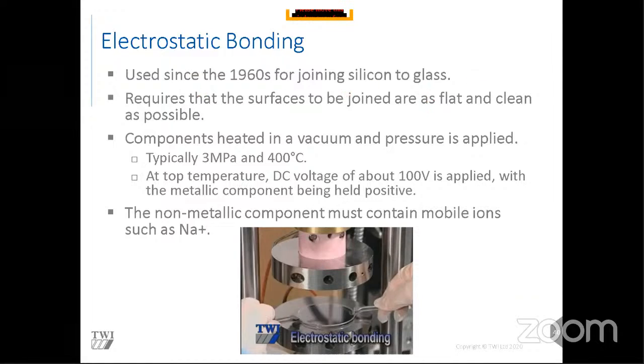The components here - so if this is our electrostatic diffusion bonding kit at TWI, this plate here, these plates move together, and your part here in the middle is what's diffusion bonded. Once these plates come together, a big shell comes down over the top, and that's your vacuum vessel. These are typically bonded at 3 MPa, at about 400 degrees Celsius.